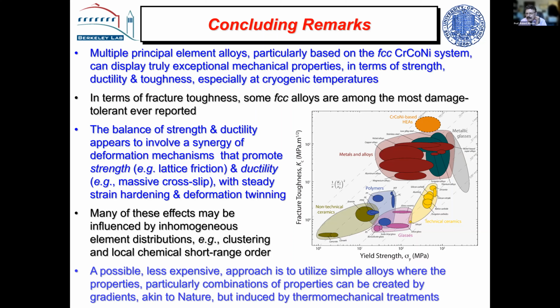We don't know. And does this have any relation also to the subsequent triggering of twinning within the context of our classical understanding of twinning? Classical material systems twin after they exhaust their capability. But the other thing about it is that you see more twins in these materials. And we think that's associated with the fact that a twin is formed by a partial dislocation moving on a slip band, right? In a regular alloy, every slip band's the same.